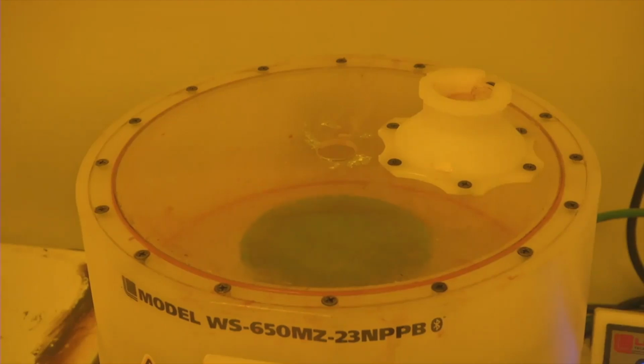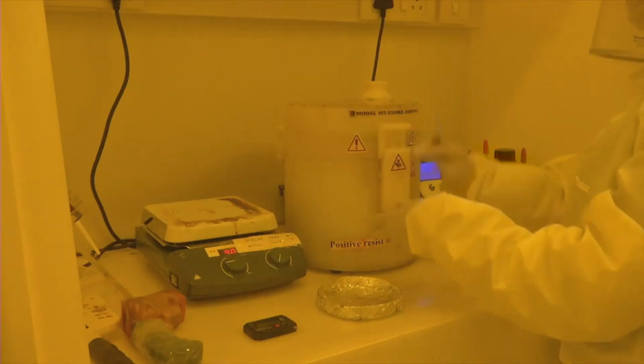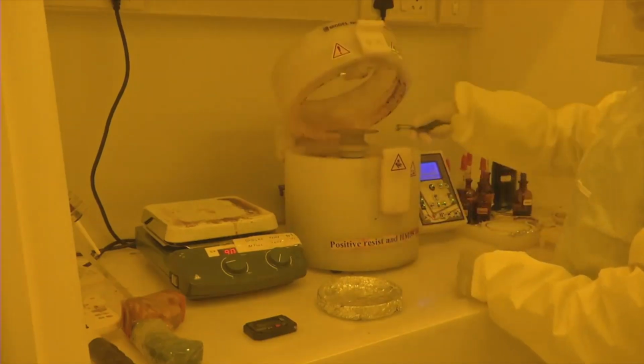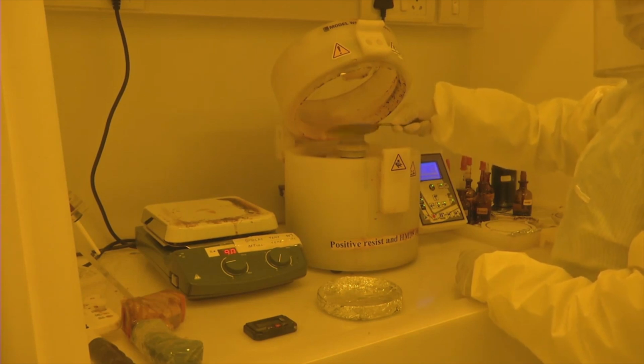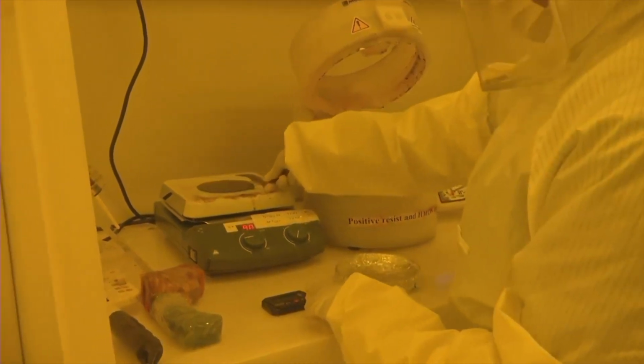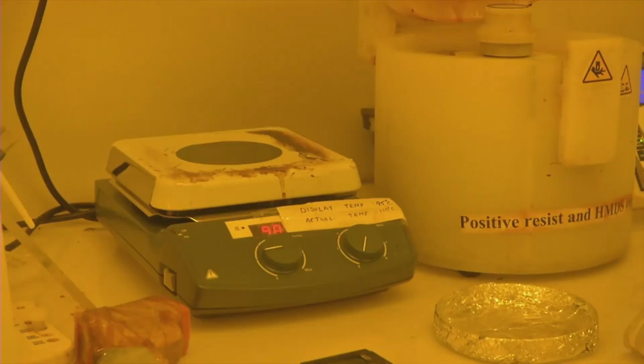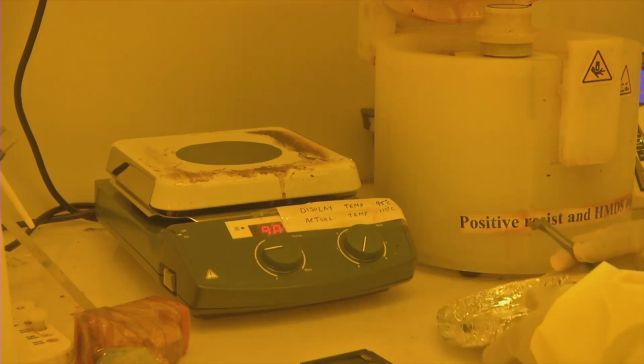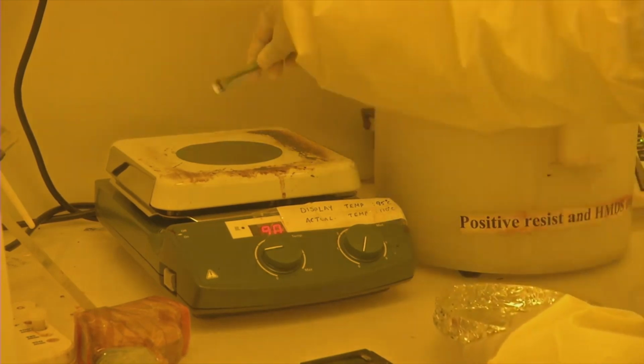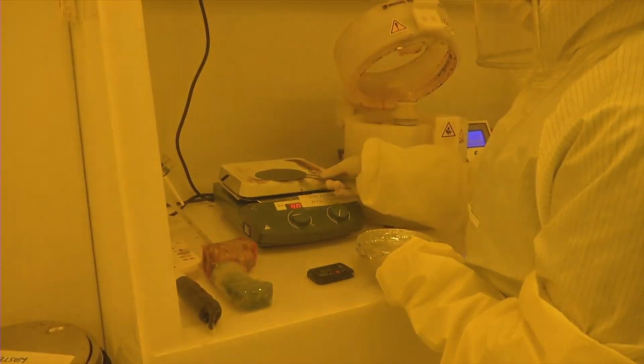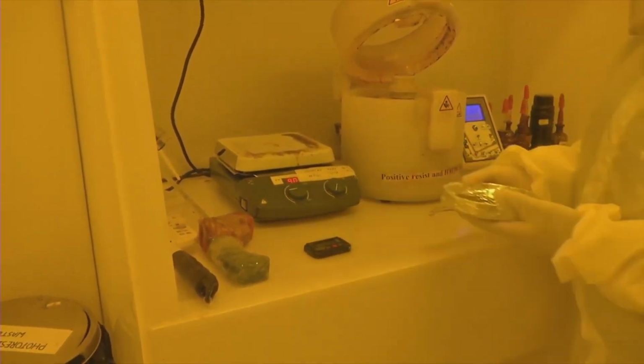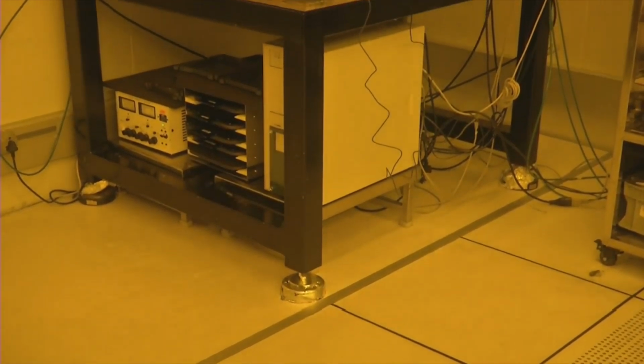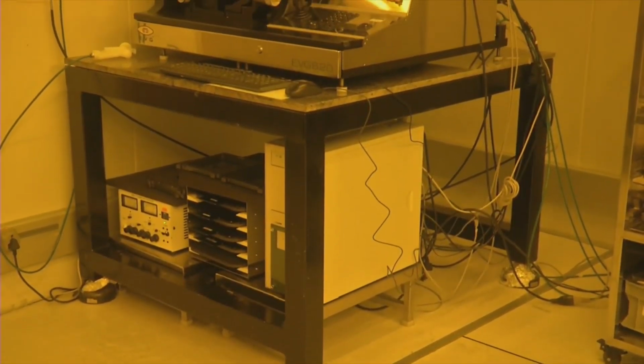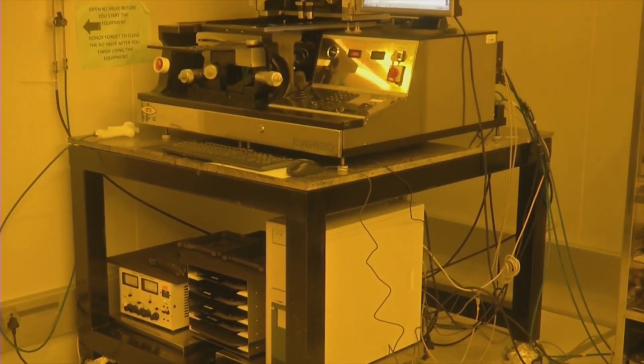Once it is there, we are going to spin it, and this spinner will rotate at various RPMs, as we also discussed during the lecture. Initially, it's going to be the spreading phase with the lower RPM, followed by higher RPM to thin it down. Once the coating is done, the wafer is taken out of the chuck, and then we are going to do a soft bake. So far the photoresist is in a slightly viscous phase, right? Now we have coated it, we want to solidify. The solidification happens when you bake the wafer. This is called soft bake. This can be done at various temperatures, depending on the photoresist material. Once you are done with the soft bake, we are going to do the exposure.